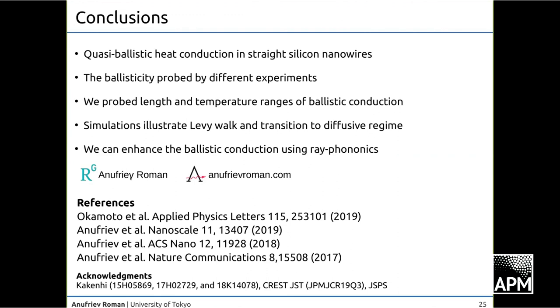We could see that it's most efficient at low temperature, but that above 200K, it's barely visible at all. And it should be below 400 nanometers in silicon where we are really able to see something. So it's not microns or something as in some works. It's really hundreds of nanometers at best. And our simulations indicated and illustrated that it looks like phonons are following somehow Lévy walk statistics. And that basically explains why it never can be purely ballistic, because there will always be diffusive scattering events,